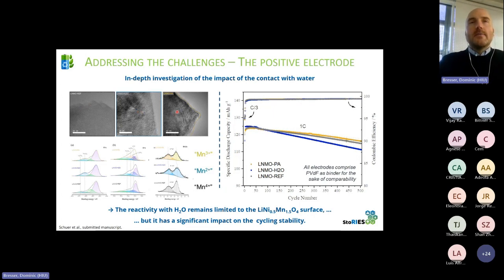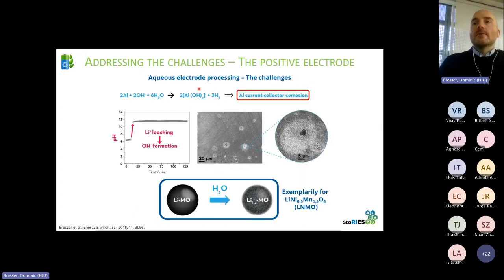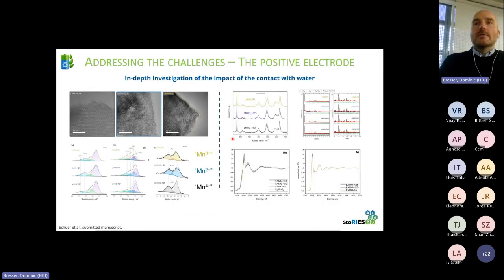I should add that if you don't only treat the material with the phosphoric acid and then process everything with NMP and PVDF, as done here for comparability reasons, but if you use water and phosphoric acid for the electrode preparation, with another binder than PVDF, then another positive impact of the phosphoric acid is that it forms an aluminum phosphate layer on top of the aluminum current collector, and then prevents the pitting corrosion that I was showing here. Right? So the phosphoric acid can play different roles depending on exactly how the electrode preparation process looks. And it turned out generally beneficial to add this.